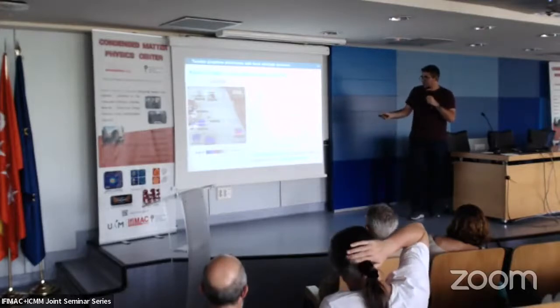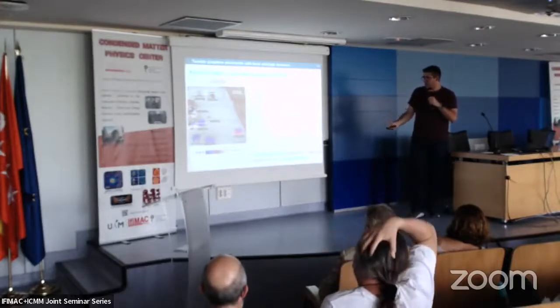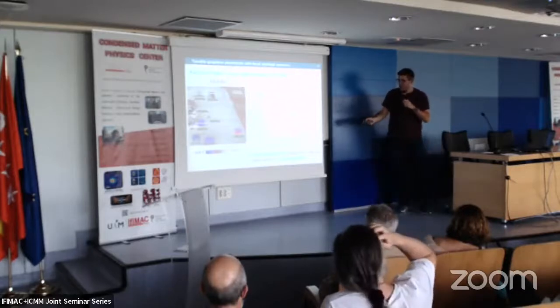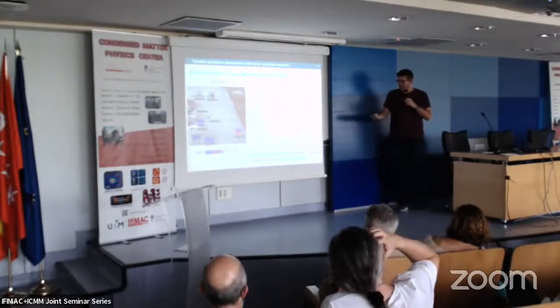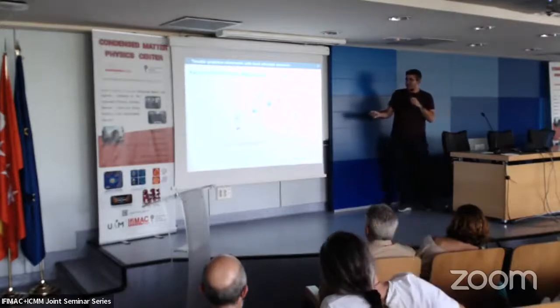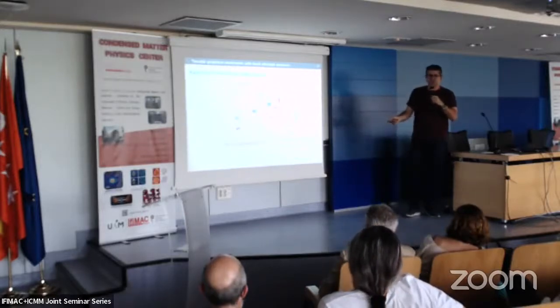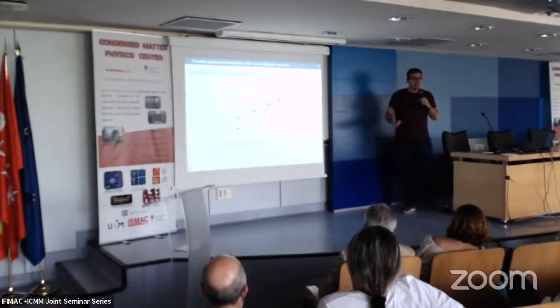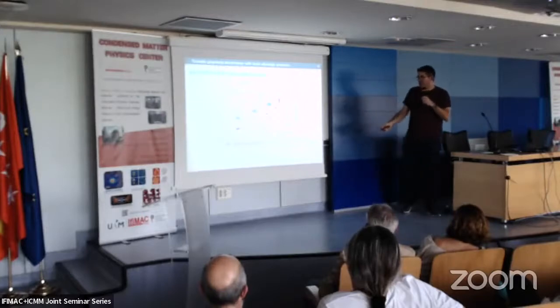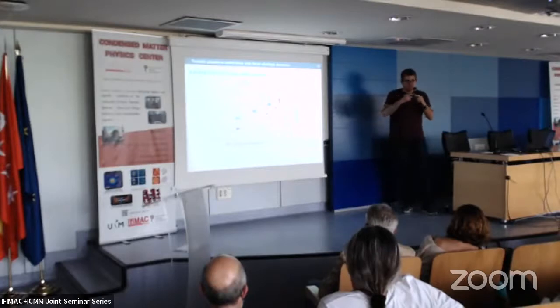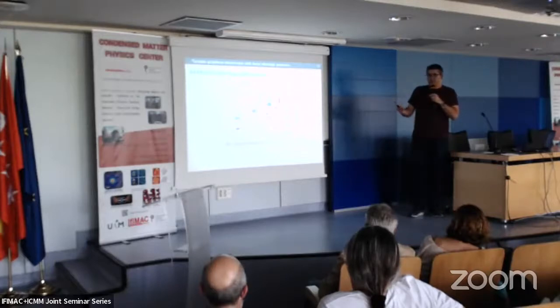The Fermi level, we can see from this plot, is shifting towards the valence band. So we are getting a p-doping effect that we can control very precisely and locally. From this data, we can also estimate the carrier concentration variation we get. This is the level of doping. And we can see that for the highest pressures, we can achieve on the order of 1.5 times 10 to the 13 carriers per square centimeter, which is a remarkable doping level, compatible with the doping achieved by electrostatic gating, but with the advantage that we can do it locally. We can do it just in a specific region and not in the whole graphene sheet based on our device. Okay, so far so good.